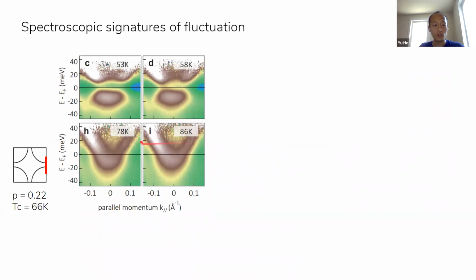Now we can use photoemission to examine the momentum structure of that spectra. What is shown here is a very high statistics, high resolution scan just along the Brillouin zone boundary. And we can divide out the Fermi function because we have such good statistics to recover some of the upper branch of the Bogoliubov quasi-particle dispersion. The top two panels are below the bulk Tc, and the bottom two panels are above bulk Tc. And I hope you agree with me that there is still a substantial band structure anomaly or disruption at the Fermi energy, even at 13 Kelvin above Tc.